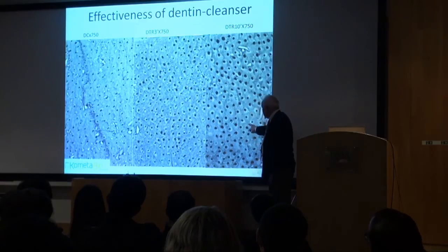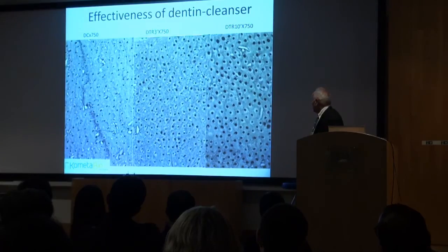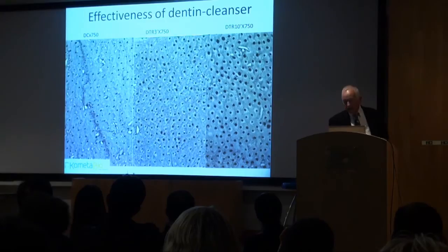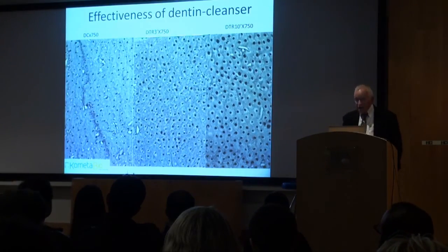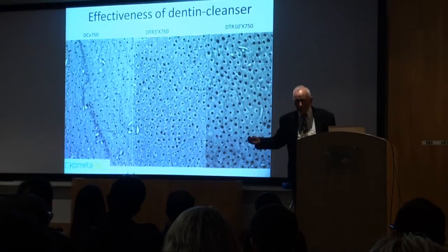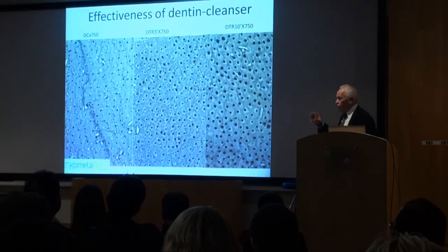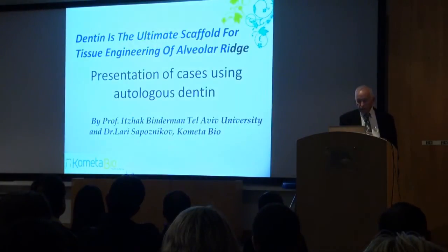But look here, all the organic material in the tubuli is dissolved after 10 minutes, and we checked it in bacteriological studies, and it is bacteria-free. Essentially, when we put in a dirty tooth, we don't even wait to see if this is bacteria-free. So from those dirty teeth, we get a bacteria-free particulate that we can use immediately.